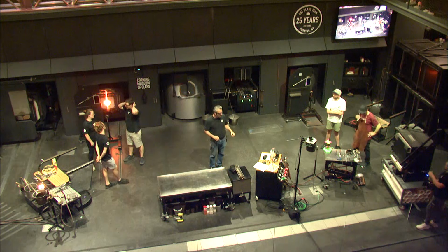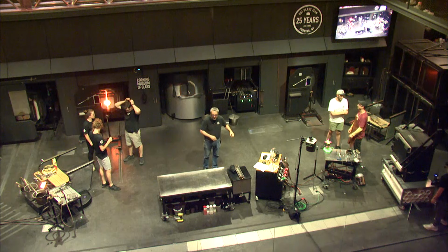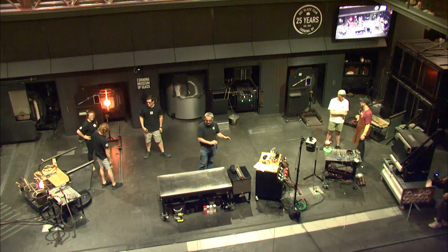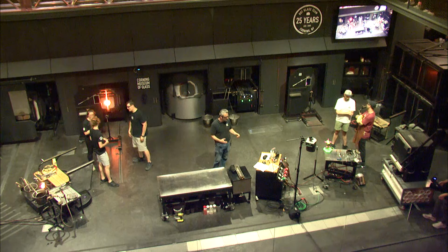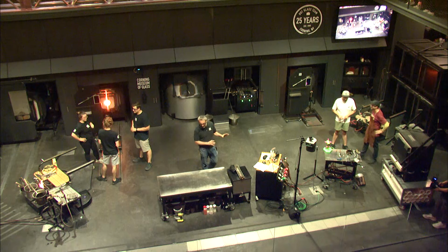We use an oven like that for really two purposes. We'll use it as a garage where we're keeping pieces warm, pull them out, continue to work on them, put them back in there. Or we'll use it to anneal glass. And annealing is that slow, even cooling, making sure all the stress is taken out of the glass so it's more stable once it's cool. If we don't anneal things, they do start breaking eventually. Some things will break within a few minutes of coming below 1,000 Fahrenheit. With borosilicate glass, if it's really evenly worked, it may not crack for days or weeks or years, but eventually that stress is going to find its way out and it will break. So annealing is an absolutely crucial step in really any glass production. Anytime you melt glass, it needs to be annealed to be a final stable piece.